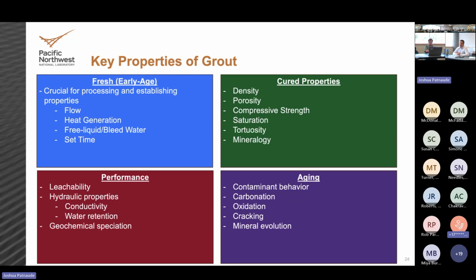The cured properties that we concern ourselves with: density of the material, that's weight and shipping if you're transporting it, but also gives us a sense of how much porosity there is. There's a direct correlation between more porosity you have, the easier it is for water to flow through. Therefore, it's easier for contaminants to flow out of it. So we usually target materials with low porosity, high density, compressive strength.